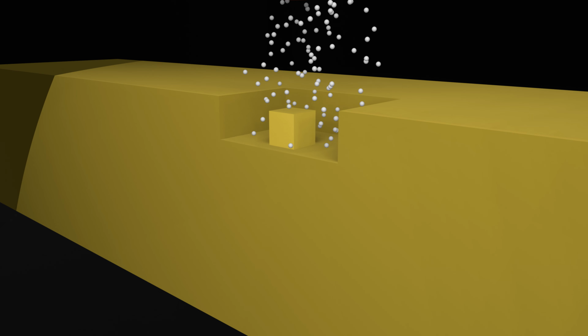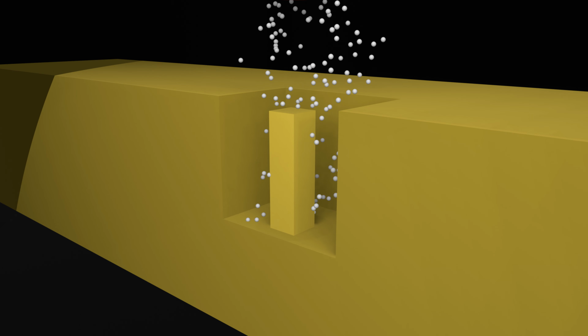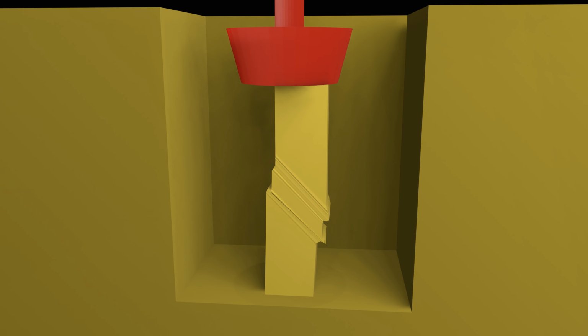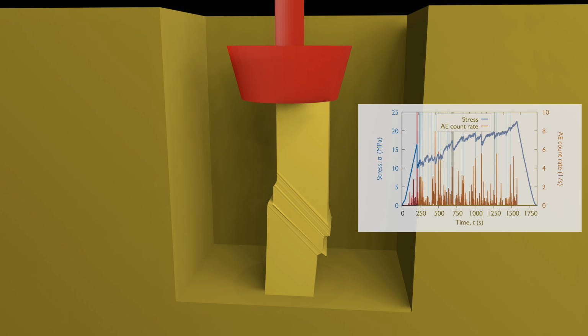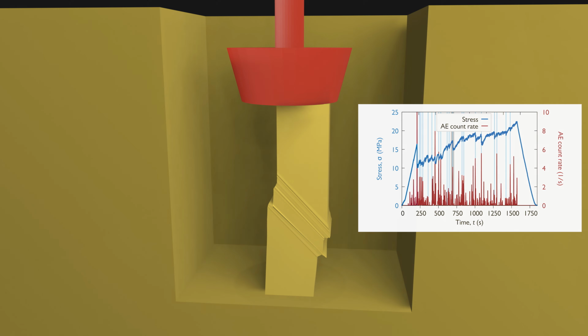Let's now fabricate microscopic samples by bombarding the material's surface with a focused beam of gallium ions and deforming them using a nano indenter. On a micrometric scale, the deformation looks completely different than on a large centimeter scale. Sudden, unpredictable stress bursts appear on the deformation curve, which are well correlated with acoustic emissions.